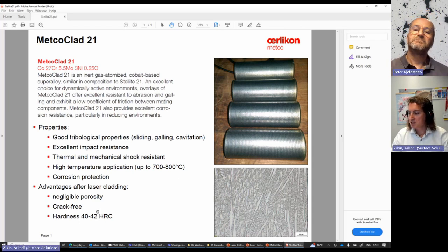Yeah. So this is a differentiation factor we see. And knowing that, it's also important to adapt your process. The best example is Stellite 6. I love this example because people usually come to me and say, Stellite 6 is one of the most used materials. It's well known. But if you do MIG/MAG deposition, you never get over 38, 40 Rockwell, which is a standard value. Then if you do PTA, you probably end up with 40, 42. I'd say with laser cladding, we get over 50.